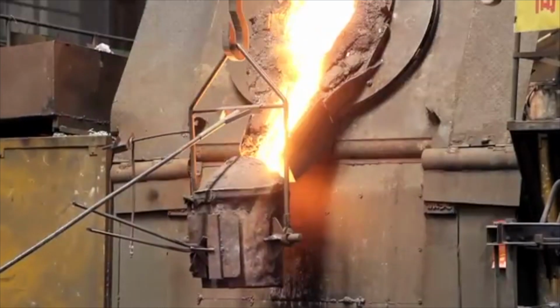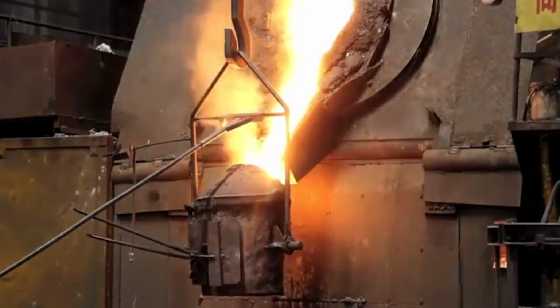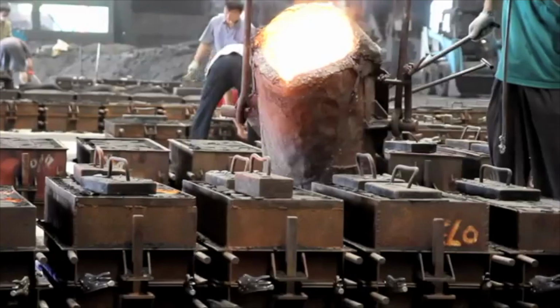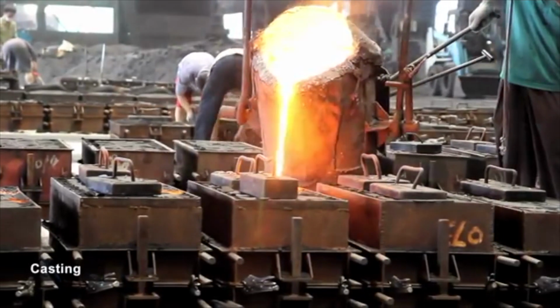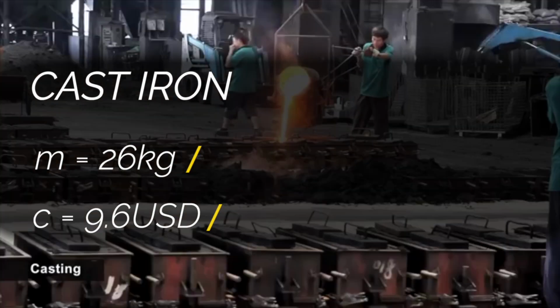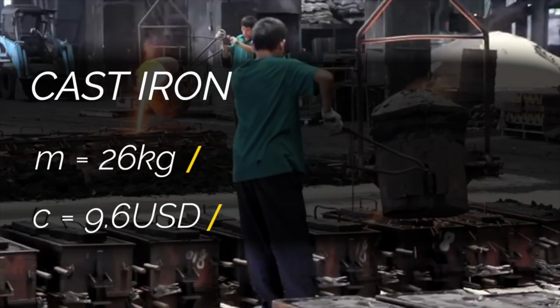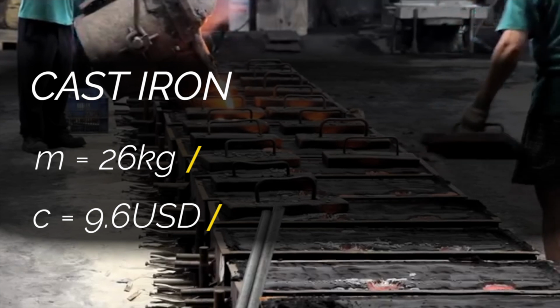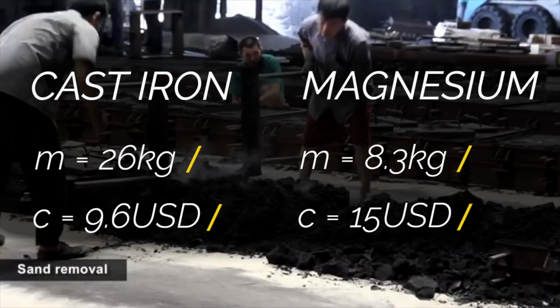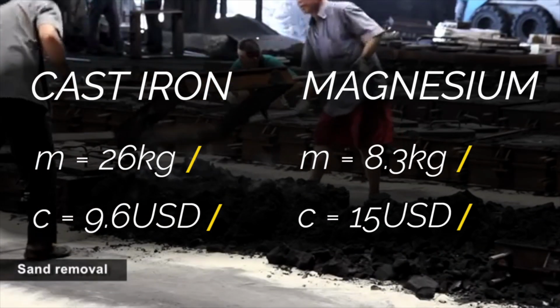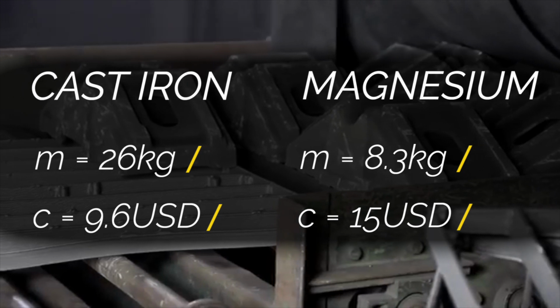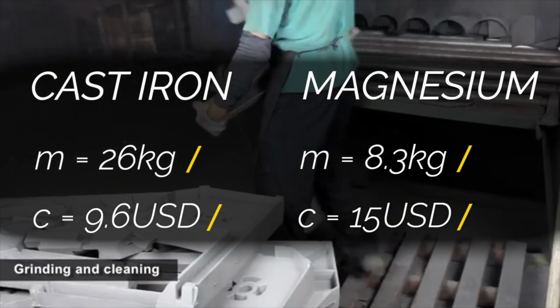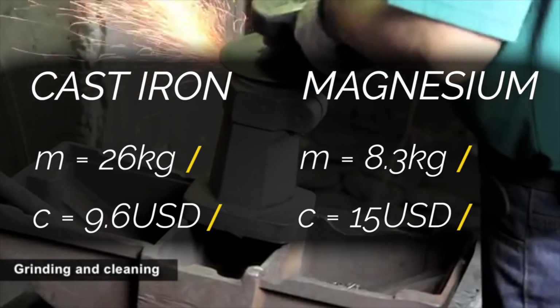It's interesting to note that cast iron was the runner-up in terms of materials. It was very inexpensive, had a high Young's modulus and a high yield strength. However, it was very dense, putting its final mass at just over 26 kilograms. The final cost, however, was $9.6 per bumper USD, about 2/3 the cost of the magnesium bumper. However, the magnesium bumper only weighed 8.3 kilograms, making it much more interesting as a whole.